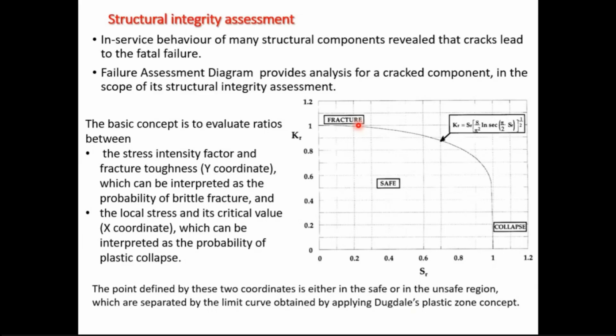Therefore, this central crack, which is in this case, let's say, only 7 millimeters, to remind you, the elbow had it for 500 millimeters. So the risk is also lower. It is in the medium region.